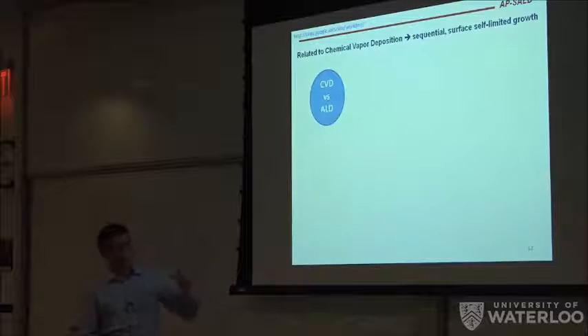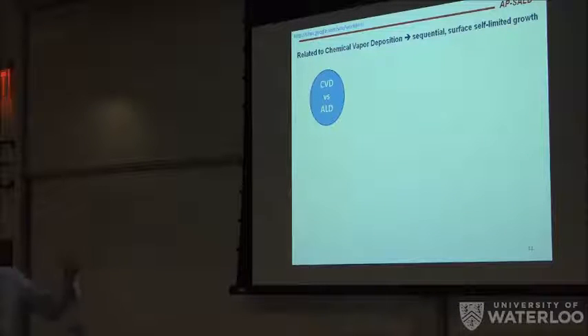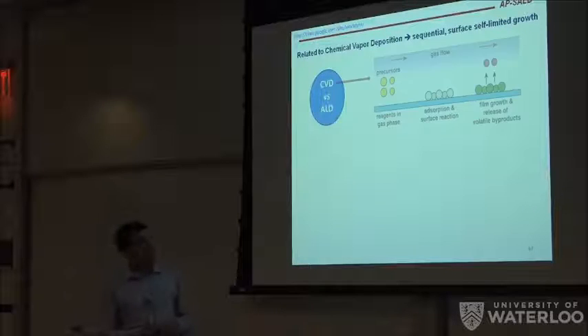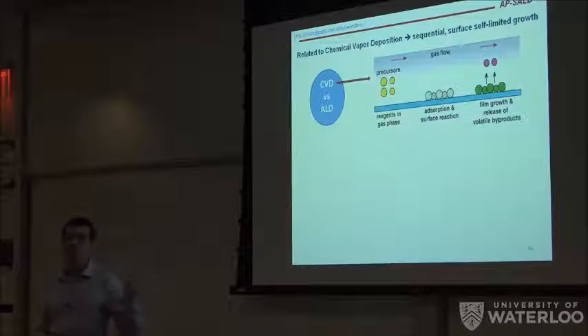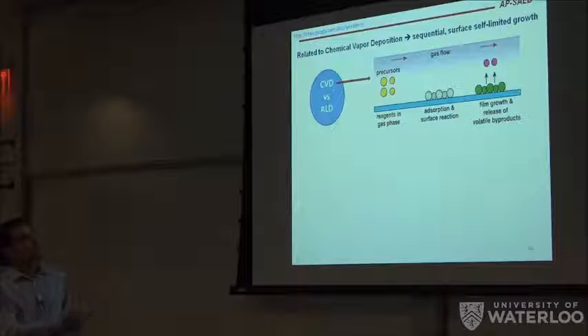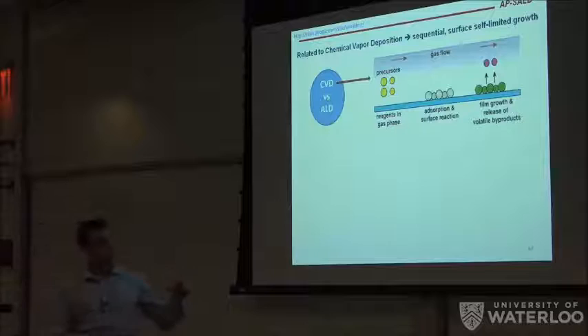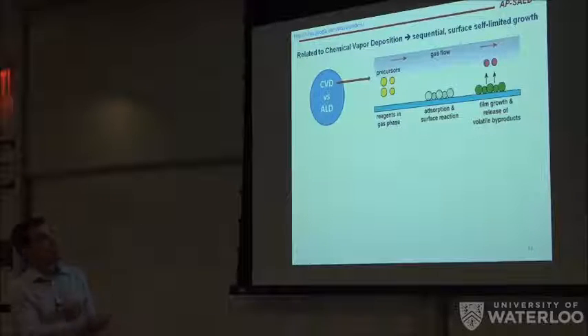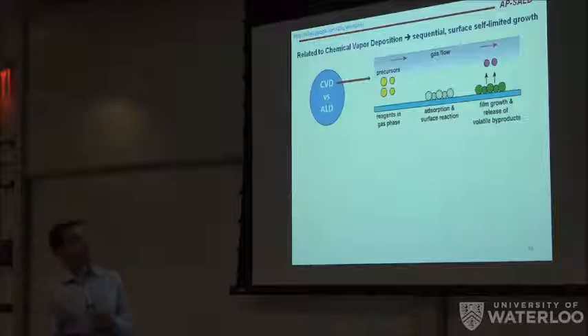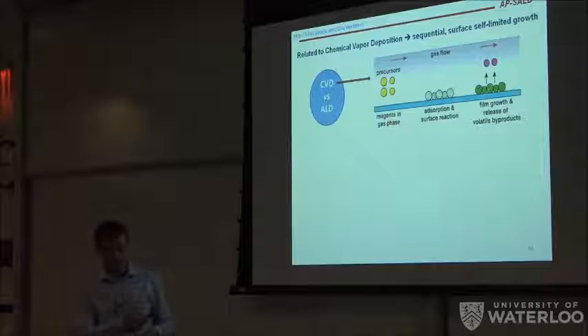So going to Spatial ALD in particular, and again, to show how important it is to find new ways of processing materials, we need to compare ALD with chemical vapor deposition, because it's very similar. In chemical vapor deposition, which has been known and used for more years, you inject different precursors in a reactor, and then they react on a substrate which is thermally activated. It's heated, so that the reaction is thermally activated, and then the byproducts are eliminated, leaving you with the film.